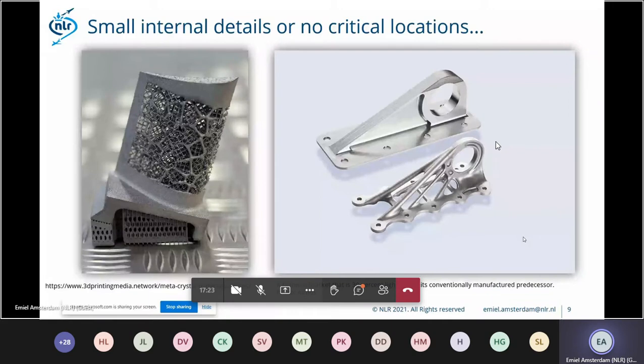However, if we use additive manufacturing, we usually make complex parts with very thin walls, and we usually use shape optimization to design the part. So here you can see, assuming a crack of 1 millimeter in such a part, you already miss some of these structures. So that's not really a feasible assumption.